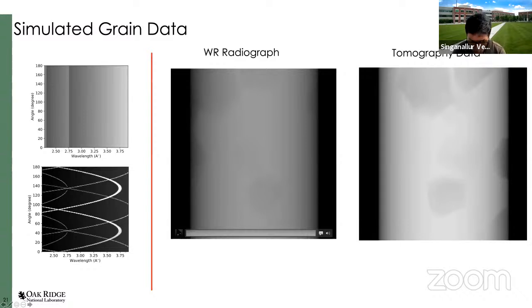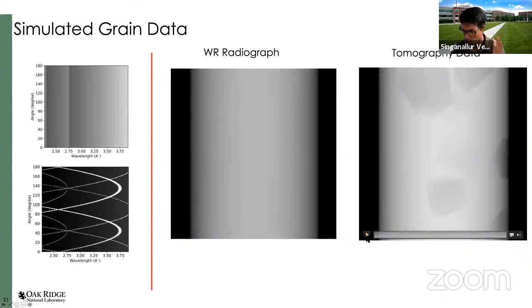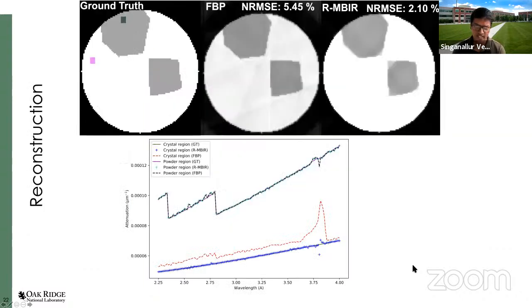We can do that with more data. Here we have simulated some more grain data, and what you're looking at is simulated neutron data as a function of wavelength. You can see that at certain wavelengths, some of the grains flicker, right? That essentially means they went into the Bragg condition. And when you look at it tomographically, when you rotate to certain orientations, there's a strong flickering due to the Bragg condition, Bragg's law being satisfied.